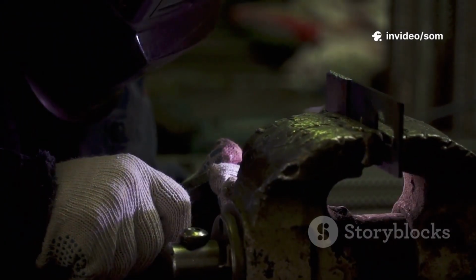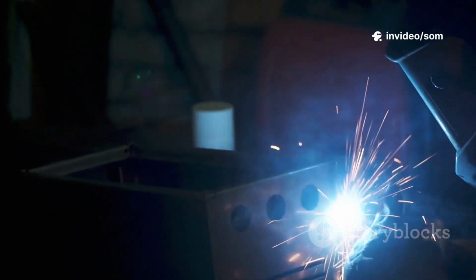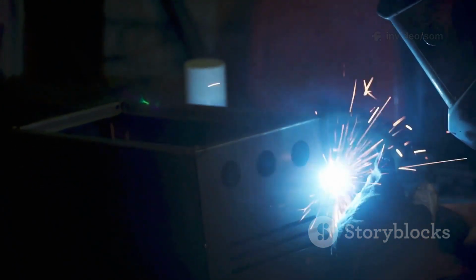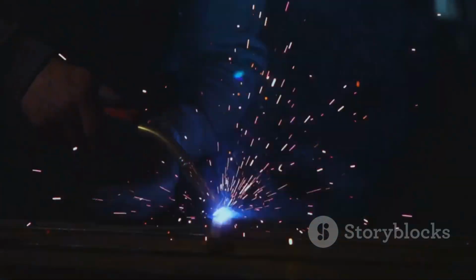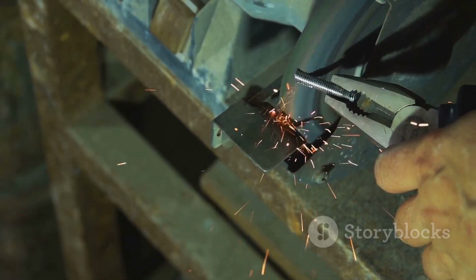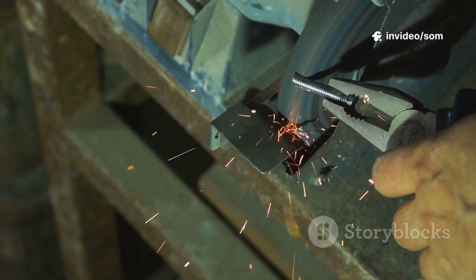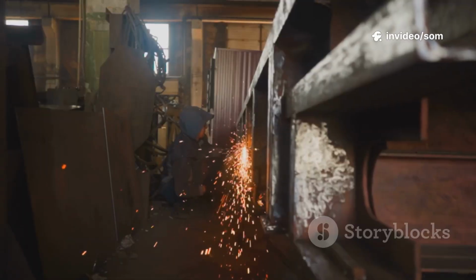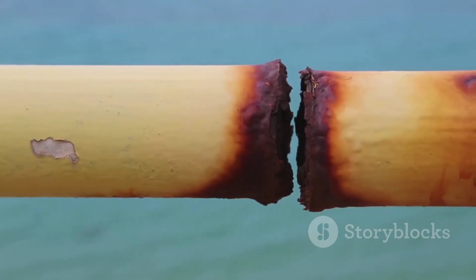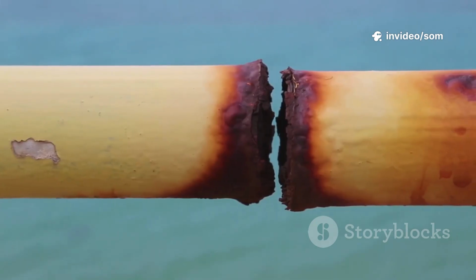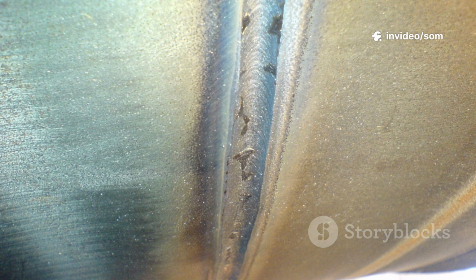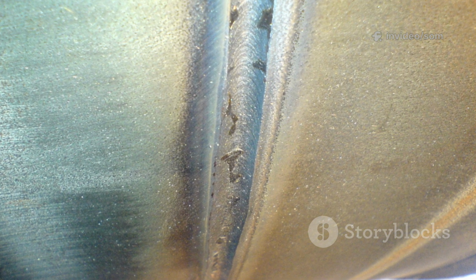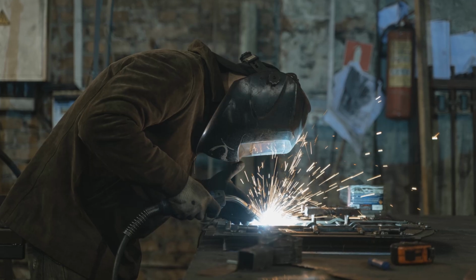Let's take a real-world example. Imagine a welder working on a high-pressure pipe for a chemical plant. He's in a hurry, the light is bad, and he doesn't clean the metal properly before he starts. He lays down a bead that looks okay from the outside, but underneath, it's full of tiny gas bubbles, a defect called porosity. For a while, everything seems fine, but the constant pressure inside that pipe pushes against the weakened weld. One day, that pressure finds the weak spots and the weld cracks. The result is a dangerous leak, a plant shutdown, and a very expensive, very messy problem. All because of a few shortcuts.